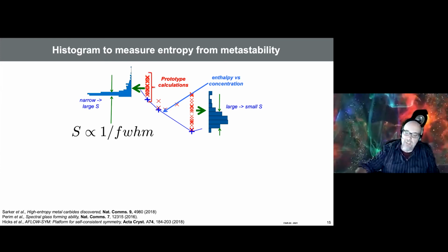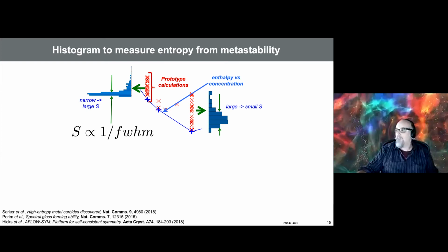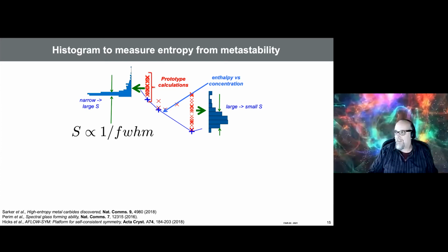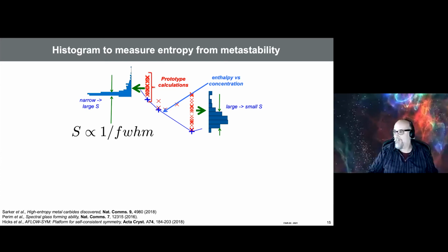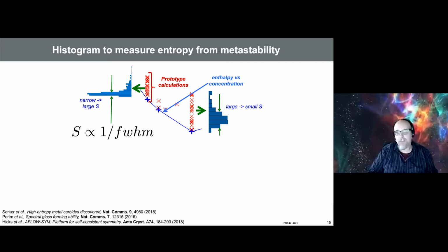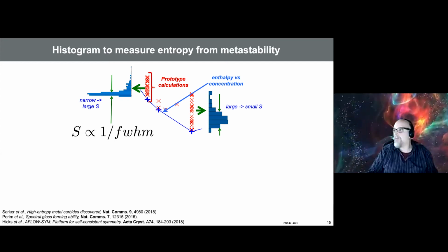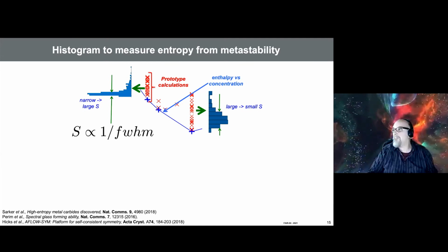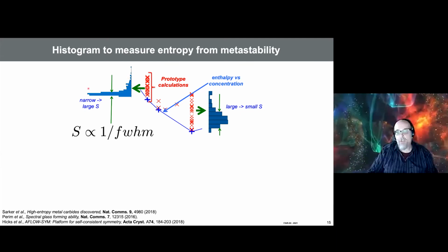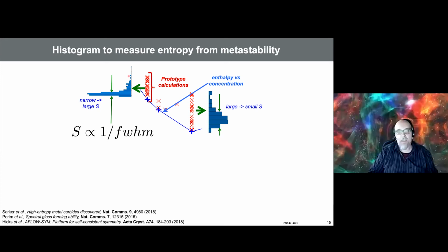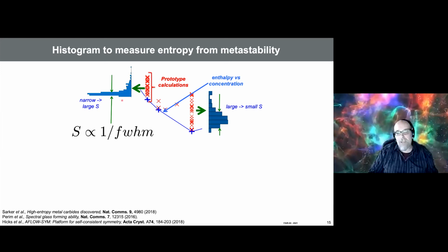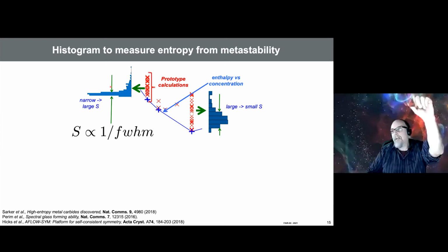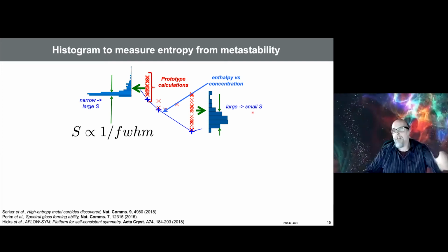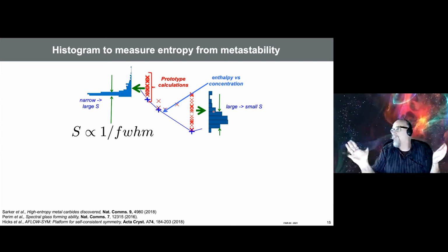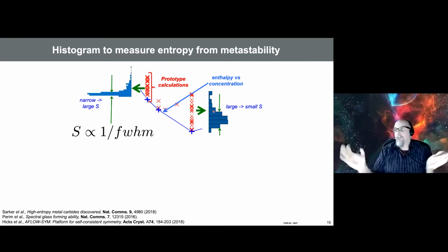The idea here holds the same, but since we have not spanned an infinite number of configurations, but only a finite number, we pretty much take the number of configurations that you have between E and E plus delta E, and this is what we call the thermodynamic density of states. If the thermodynamic density of states has a very thin peak, then you have a high entropy. If it is very broad, then you have low entropy. It's simpler than that.